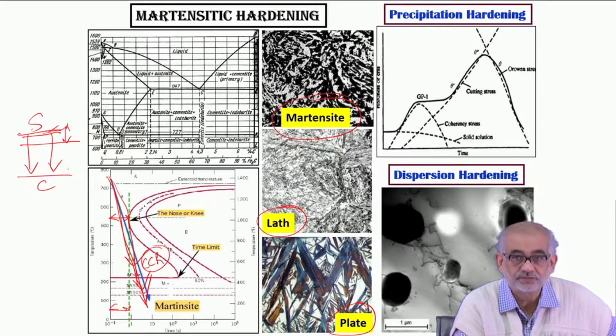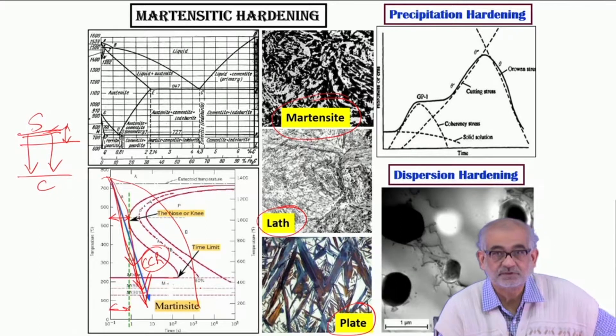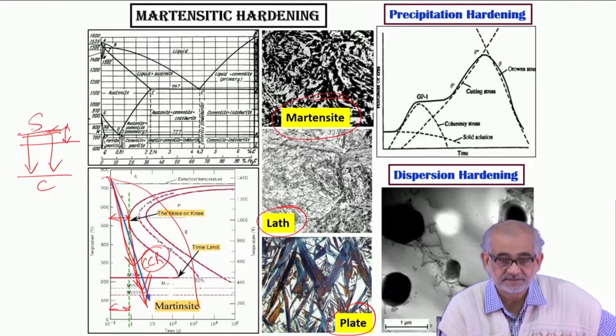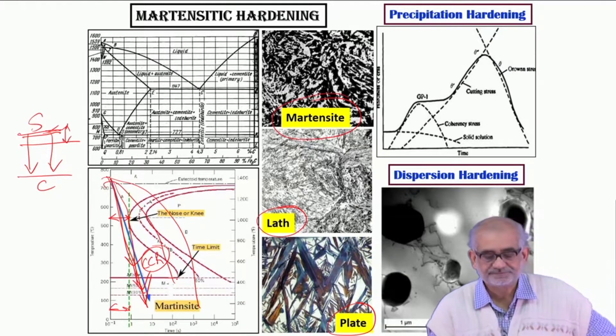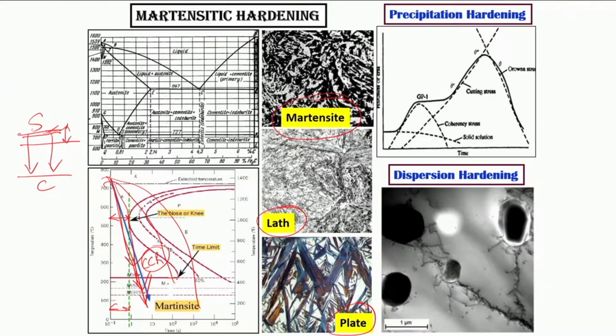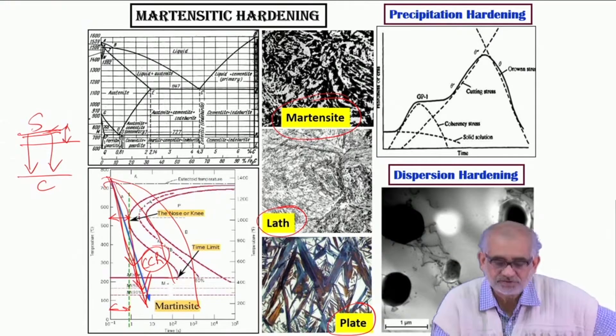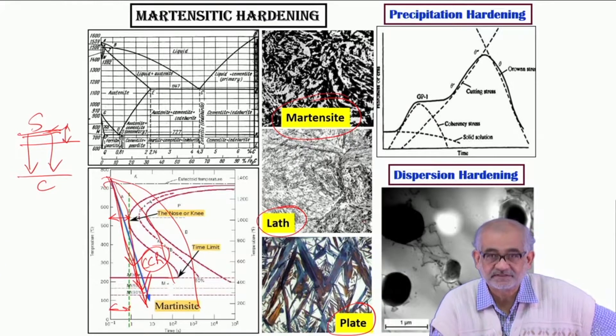So below this depth the cooling rate will be lower and hence we end up getting a microstructure which can be just purely coarse pearlitic or fine pearlitic. When we talk of carburizing, it is all about martensite - the strength comes from martensite, nothing else.